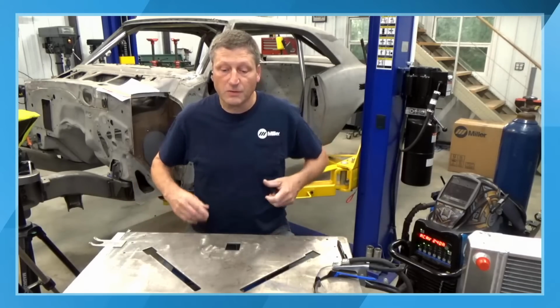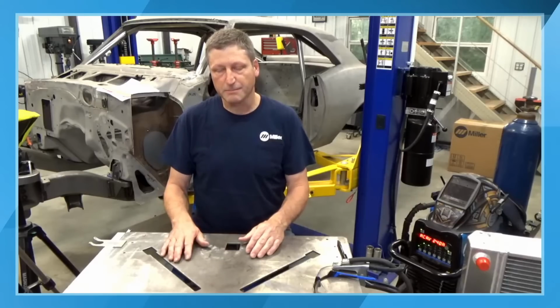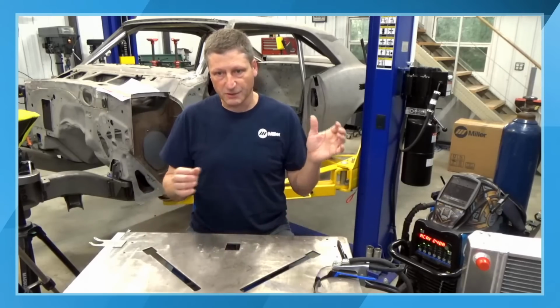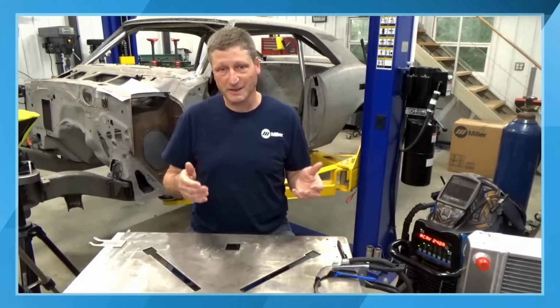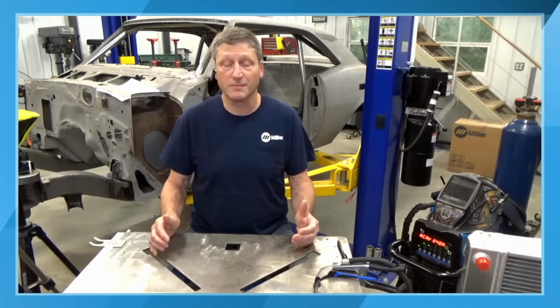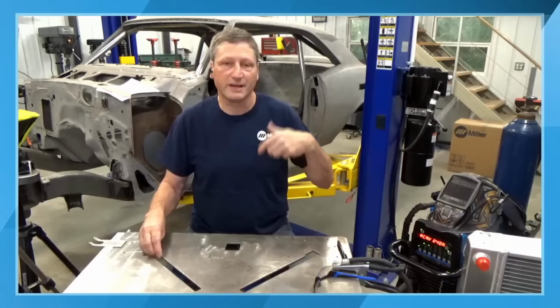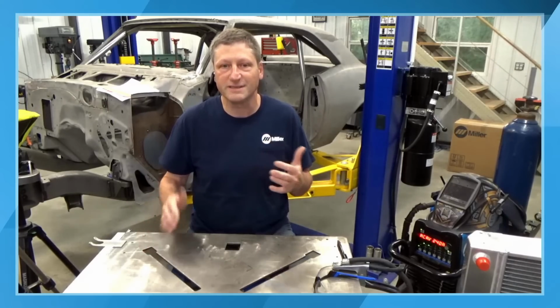Certain alloys, yes, but most of the time the as-welded condition will be no. For example, certain filler metals are not post-weld heat treatable. So if you're working with, let's say, a billet cylinder head and you're welding this up, it's really not feasible on a one-off item unless you have the ability to do some high temperature controlled areas, where you can put this thing in a temperature controlled oven at X amount of temperature for X amount of time, and then you're stepping it down. It's not nearly as easy.